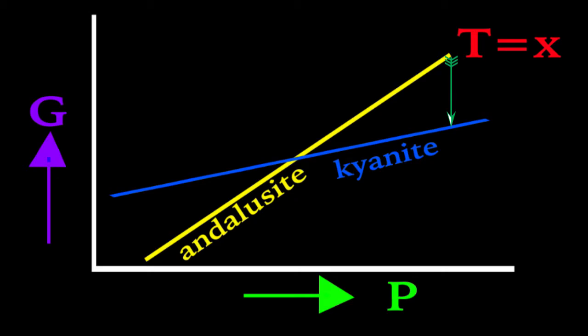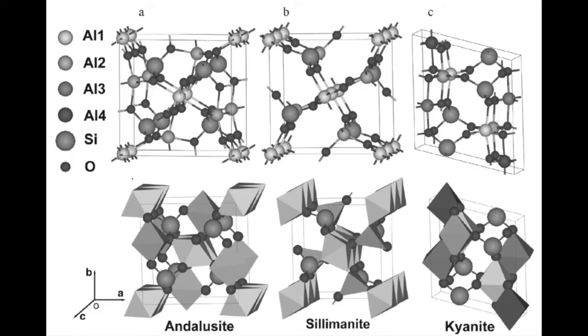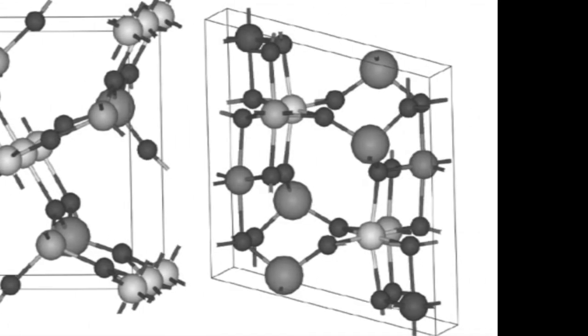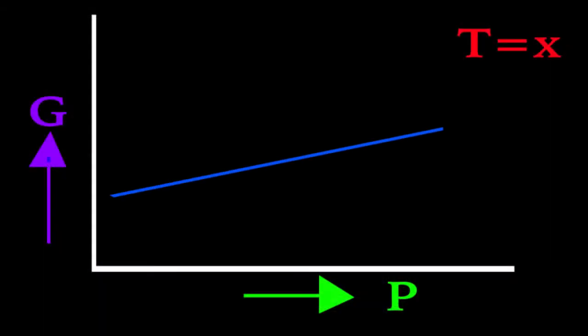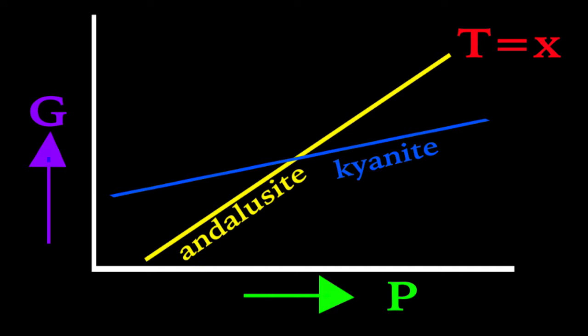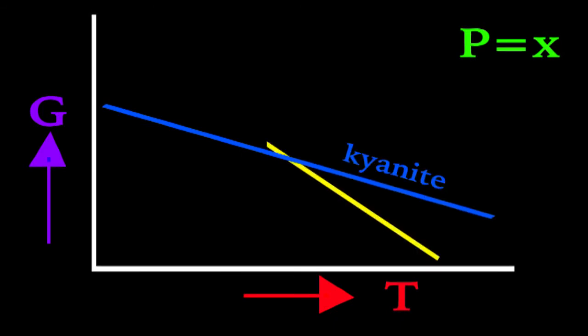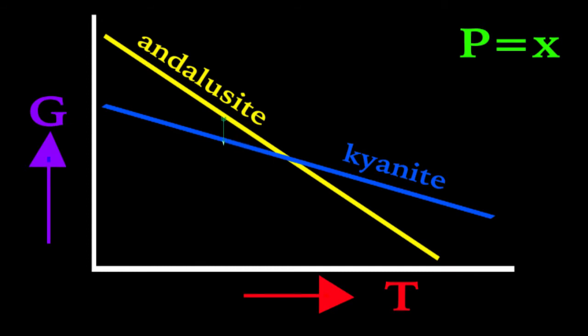A physical explanation for this is that when you put the atoms of Al2SiO5 together to make andalusite, it's puffier, with a greater overall volume for the same amount of atoms — or we say it has a higher molar volume. Kyanite packs its atoms together closer, and thus is less stable at low pressure and more stable at high pressure. Of course, there is a particular value of pressure at this temperature where the two phases have the same Gibbs free energy, and this is a point where the two minerals can coexist — in other words, a point on the univariant curve between these two minerals. The other graph over temperature is read similarly: at lower temperature, kyanite is the stable form with the lower Gibbs free energy, but at high temperature, andalusite has the lower and thus more stable Gibbs free energy. The intersection is again a point on the univariant curve between kyanite and andalusite where the two can coexist.